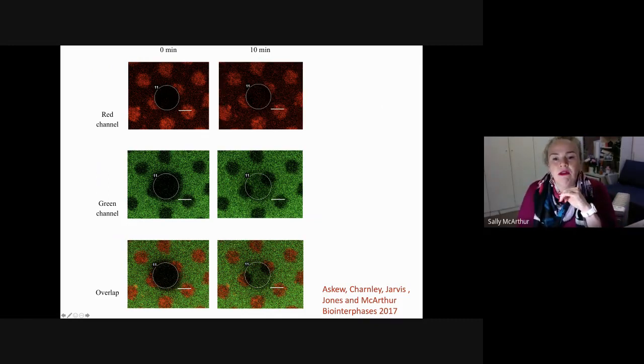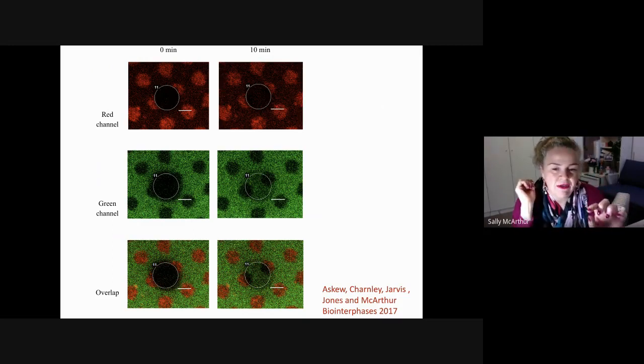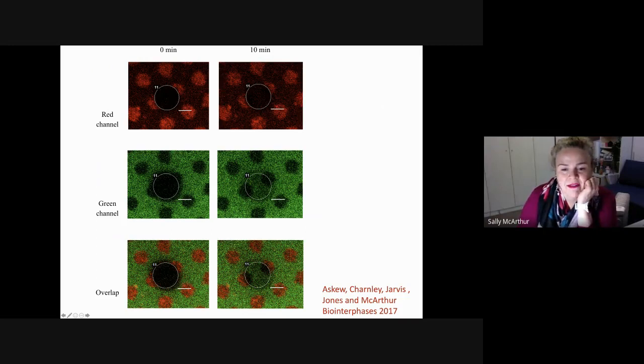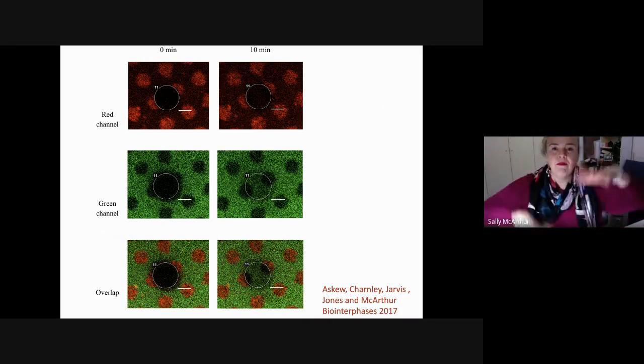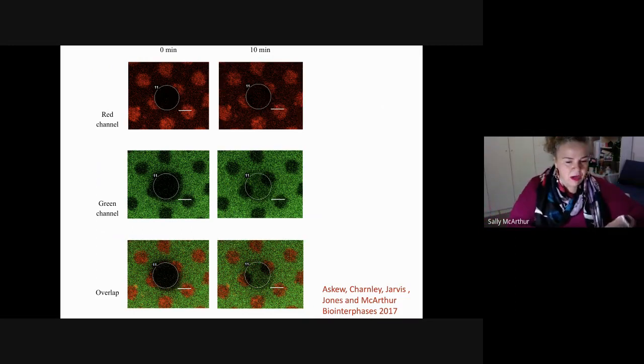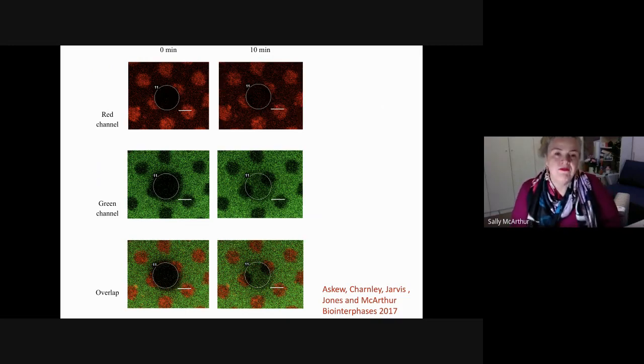So the area of green where the lipid's able to move around is mobile, but up on the pillars or up on the actual surface areas that are the different chemistry, the red zone where the red lipids are, they're not able to recover. They stay dark. So we've retained that mobility, and now we can have an area of mobile lipids sitting next to an area of immobile vesicle as well. So that's just a different way of putting these systems together.